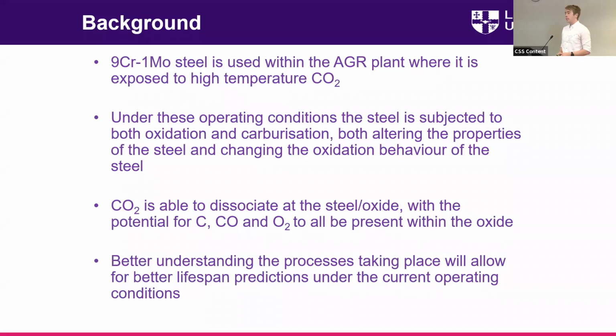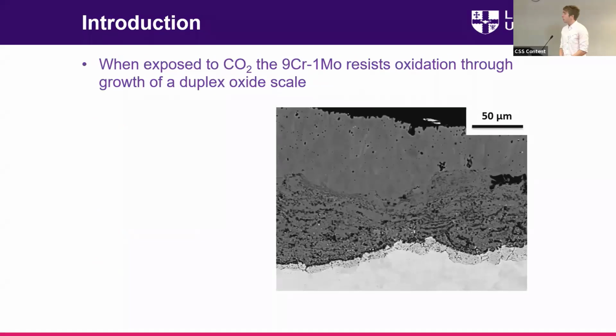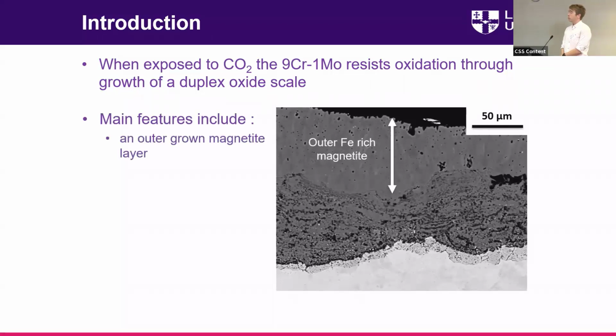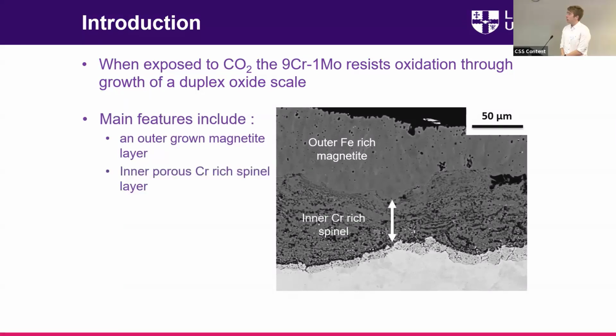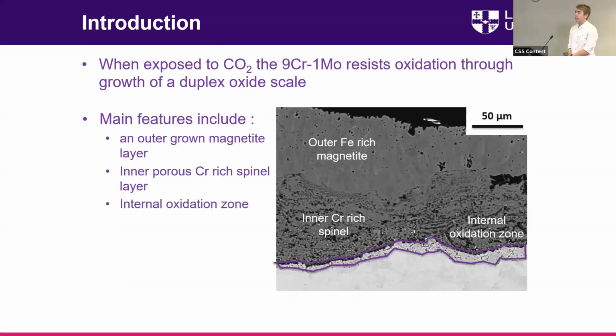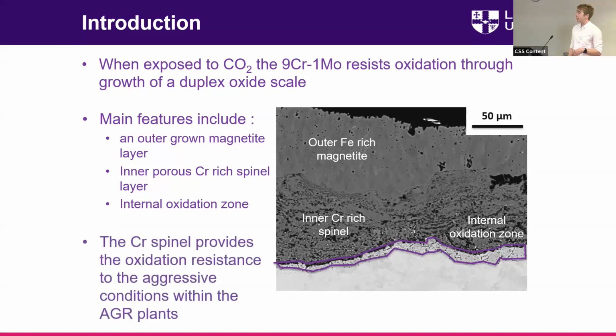So better understanding of this process will allow for better predictions and understanding of the aging that's going on within these plants. When it's exposed to CO2, it resists the corrosion through the growth of a duplex oxide scale, which consists of an outer magnetite grown out from the original interface, an inner porous chromium-rich spinel, and there's also an internal oxidation zone, which is present growing in ahead of the spinel layer. It's the chromium-rich spinel layer that's thought to provide the oxidation resistance.